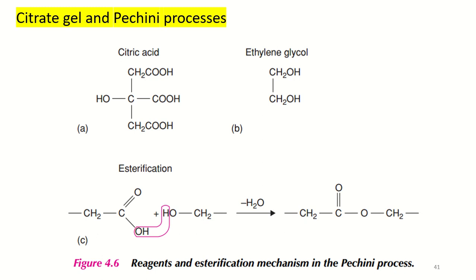The citric acid also acts to control pH during reaction, in particular to avoid precipitation of insoluble citrates, which would lead to loss of homogeneity during the intermediate stage of reaction or in the final product.